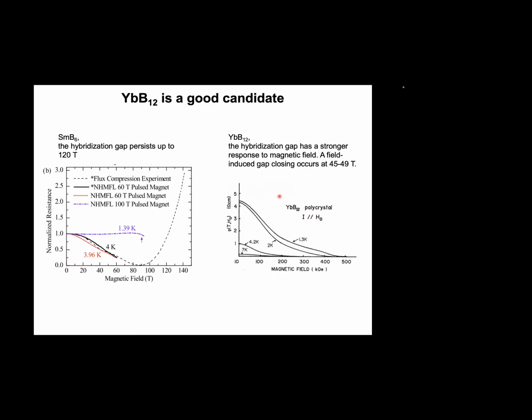I know the compound SmB6 failed, but we may try some other Kondo insulators with either narrow gap or lower gap closing fields and see what happens. Since I'm running out of time, I will just quickly present the observation. In SmB6, we find the maximum field, 80 or 100 Tesla, is not doing anything. Actually, a few weeks ago, there was evidence suggesting even 180 Tesla is barely closing the gap. So we do not have magnetic fields in this range closing the gap.